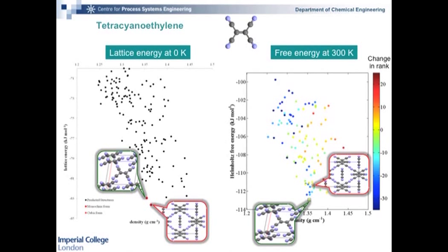And so here again, all the structures, and here are the best ones we found. And so the lowest one is the cubic form, which turns out to match the experimental data. And we found less stable a monoclinic form here, again, in agreement with the experimental data.